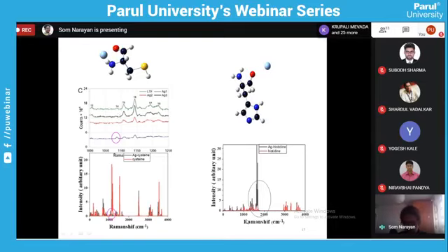cysteine. And in a similar way, there is an enhancement we can see in this peak. It is due to the interaction of Ag with the histidine. So you can see that the molecular mechanical approach, together with the quantum mechanical approach, is very useful to get some of the reasons why we are getting this kind of Raman spectra, due to the interaction between the particular Ag molecule with the histidine or cysteine or these ligands.